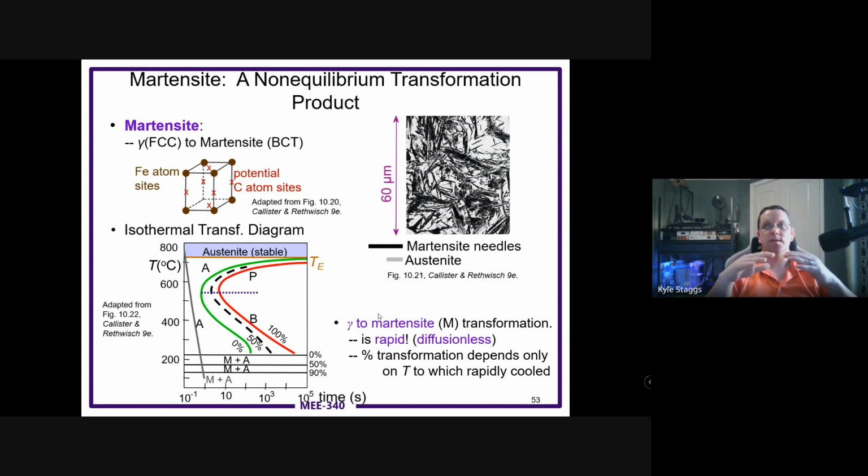and alleviate stresses, right? Whereas you saw some of the steel samples that fractured on a diagonal, you saw those slip planes actually form, and the material slips and slips and slips until it finally doesn't have enough energy to maintain connection and then releases, right? So they were always diagonal, and that's those slip planes showing up. These materials, these martensites, don't have that to the same degree. So that's why that hardened steel has a much sharper shard kind of fracture than the even cup and cone fracture of a mild steel. It's because of this particular grain structure. That's why it separates and is jagged the way it is.